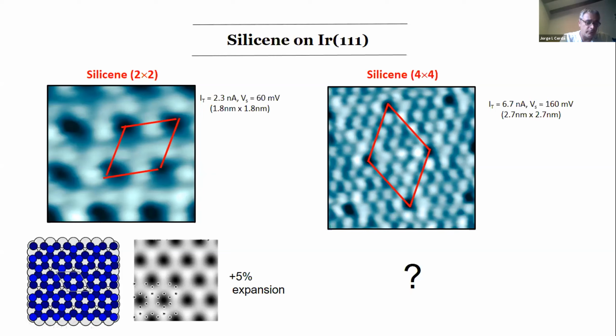Actually, when you remove one of these silicon atoms, you have all these dangling bonds that give a really bright signal on the STM image. So we don't really know the nature of these holes yet. The system is quite complicated because these are really out of equilibrium phases, low coverage islands, and they don't typically cover the whole surface. And I'm thinking that maybe we'll have to go into thermodynamics soon to try to understand it. Okay, so that's all for now. Thanks a lot for your attention, and thanks to the organizers as well.